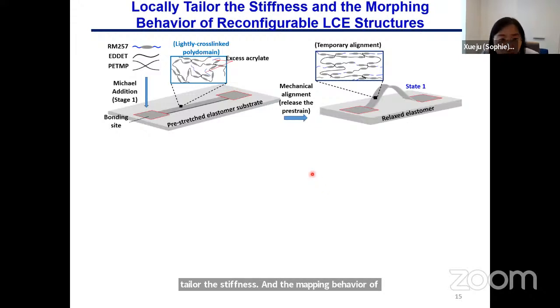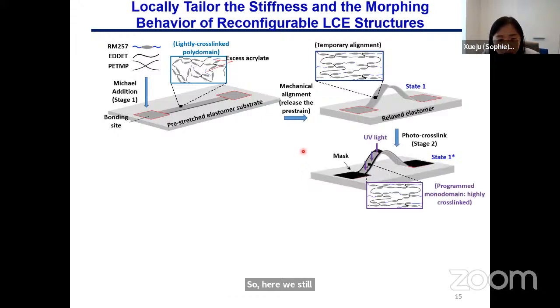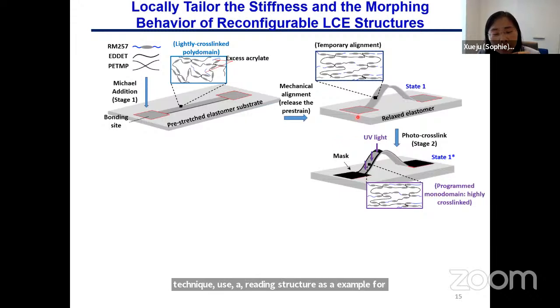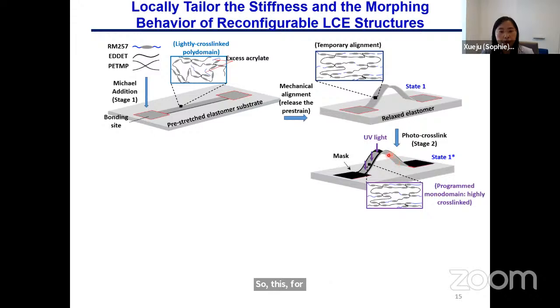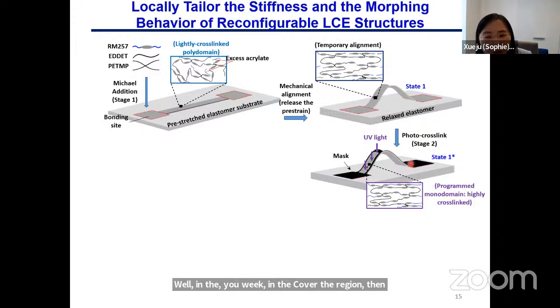structures. So here we still adopted the buckling technique, using a ribbon structure as an example for the study. But here, instead of blanket UV exposure of the entire structure, we used a photo mask to enable selective photopolymerization. For this ribbon structure, we used a photo mask to cover half of the structure. Then in the UV exposed region, you can see that the mesogens are highly cross-linked, and their alignment is permanently programmed. In the covered region, the mesogens still maintain a lightly cross-linked state, and the alignment is not programmed.